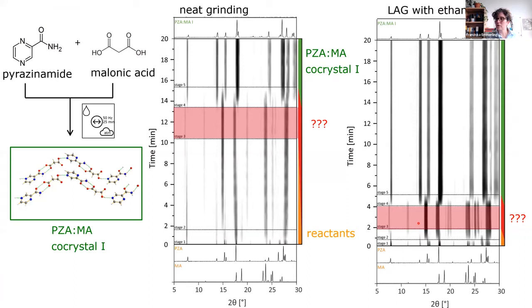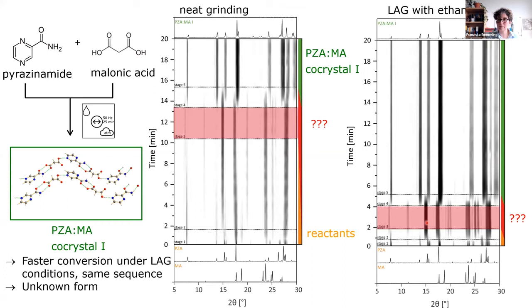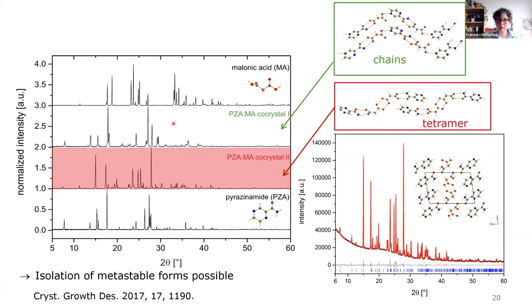So what we could do then is stop the reaction, prepare a sample, measure it, and then solve the crystal structure from the powder pattern. What we can see here is a general trend that usually under liquid assisted grinding conditions, the reaction is faster. So this is the resulting crystal structure. You can see here we have a chain structure for polymorph one, and for this new polymorph, we have a tetramer consisting also of a homosynthon here.